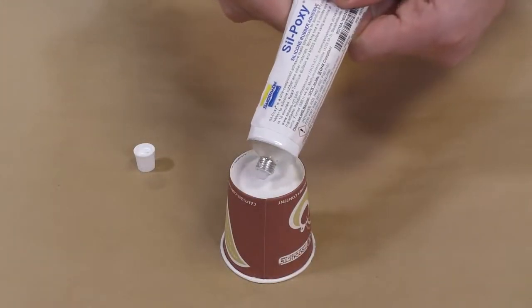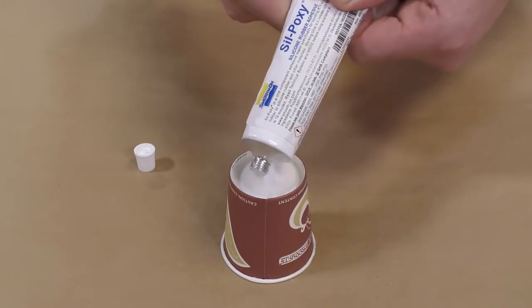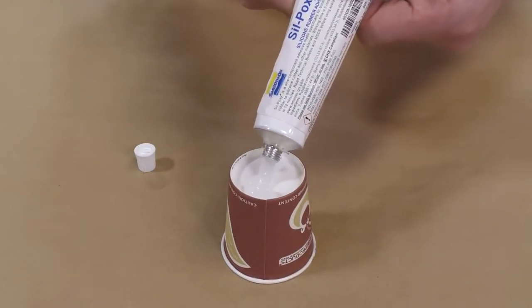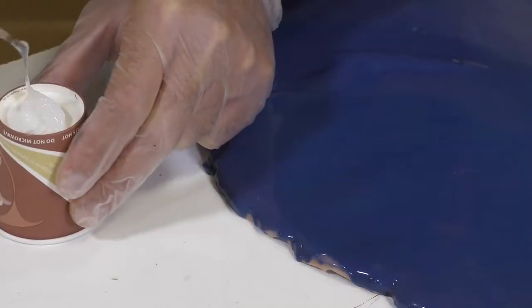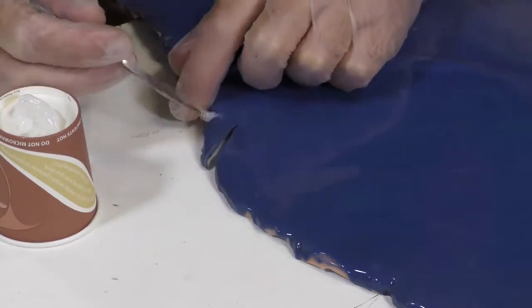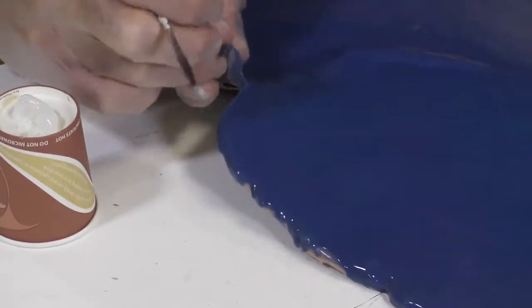I am going to dispense the Sil-Poxy onto the back of a cup and use the lip on the cup to help me contain the material. Sil-Poxy has a five minute pot life once it is dispensed so we need to make sure we work quickly.